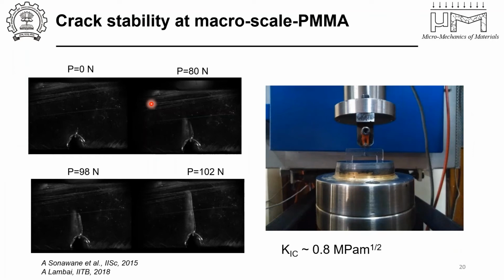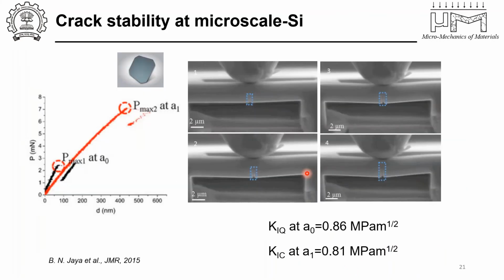So this crack stability was demonstrated at both bulk and the micron scale. This is a sample that was carried out in IISc, where you see that at different loads, you see a stable crack growth in glassy structures and in PMMA, and with higher and higher load. But the K1C of the material was constant. If you measure the K1C at each of these individual load drops that we saw, then it would be a constant because it's a monolithic material. The fracture toughness of the material is not changing, but you can achieve stable crack growth.